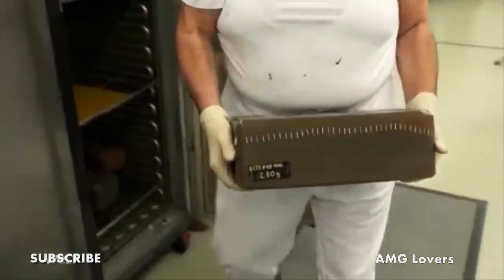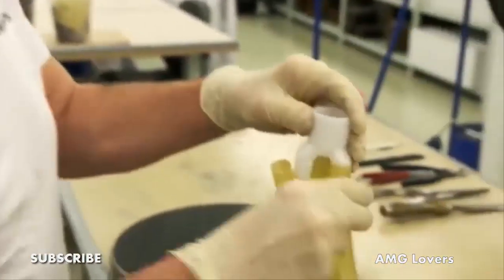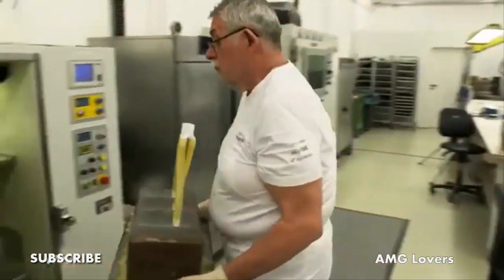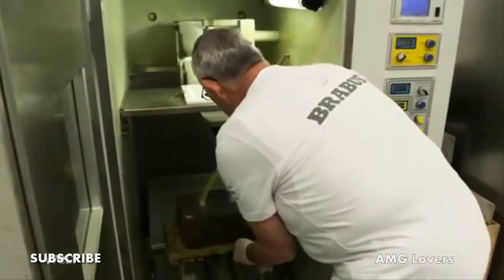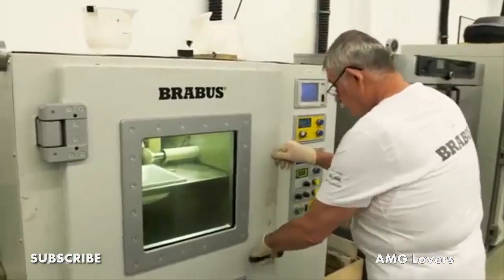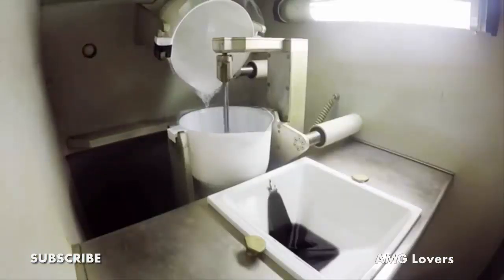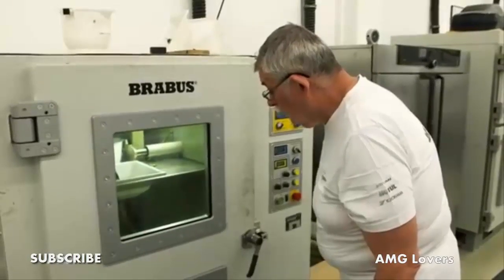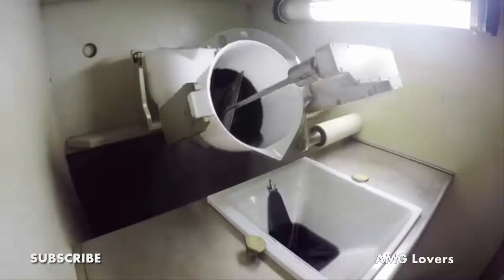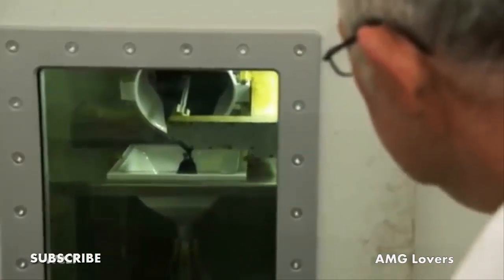Now, the materials engineer takes the silicone block from the curing oven and fits it with 3 filler hoses. He then also puts the finished mold into the casting machine. The 2 components bind to form polyurethane in the casting machine. The black resin provides excellent dimensional accuracy when casting high-quality molded parts. To avoid the presence of abnormal cavities caused by air pockets in the finished workpiece, a strong underpressure is used in the machine.